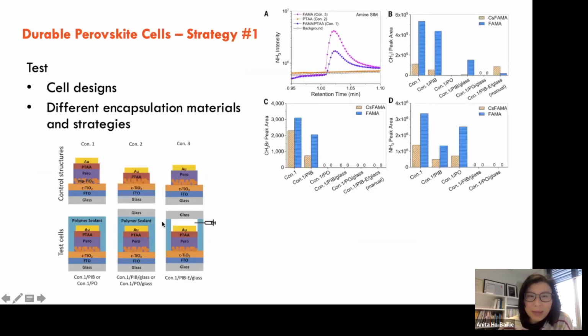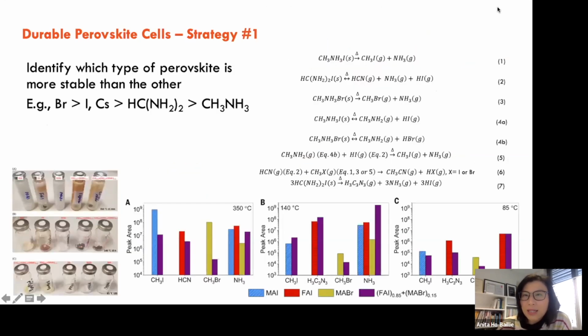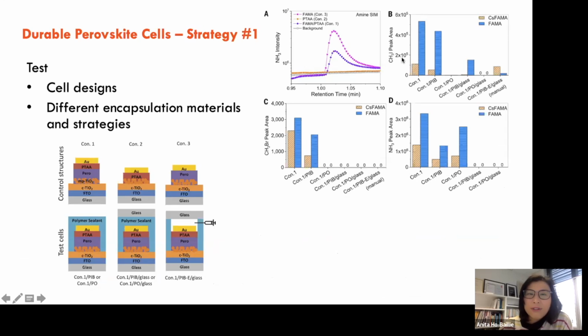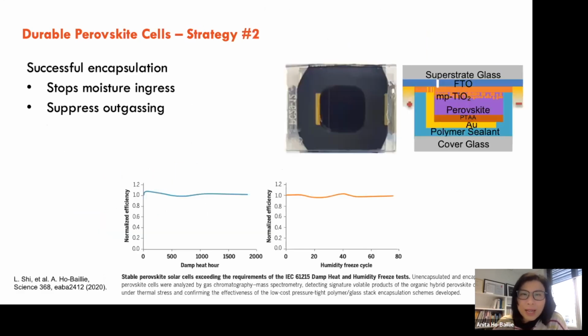So what's happening? The polymer is good at stopping moisture from going into the cell. Perovskite doesn't like water. Actually, most optoelectronic devices don't like water anyway. But the blanket approach actually stops the outgassing. You can see that these are the outgassing products. When they degrade, stuff comes out, and we call it outgassing. Now, if you have the blanket, it just covers it, there's no void, and therefore it stops the degradation reaction from proceeding forward. And so we have successfully found a way to stop moisture from going into the cell and to stop the outgassing from the perovskite.